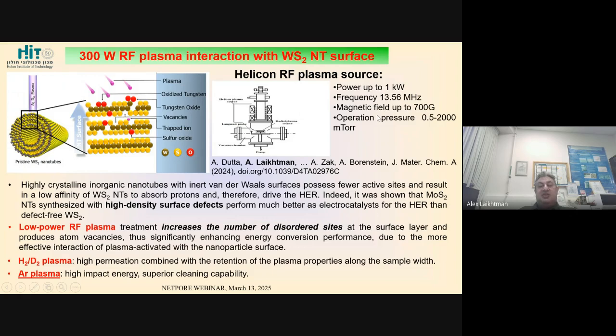In such a case, the temperature is still about room temperature, so we don't heat the samples. So this is cold plasma. And then there are either argon or hydrogen. I will tell you later why we're using these gases for the plasma. And after this plasma treatment, we have very dramatic changes and enhancement of the properties of these WS2 nanoparticles as catalysts. So I will start from the end.